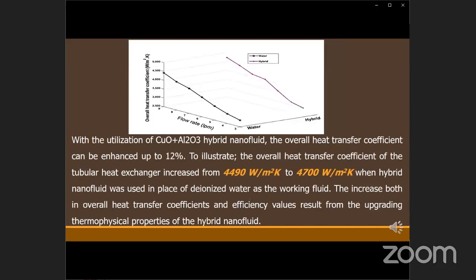heat recovery units. And finally, with the utilization of copper oxide alumina hybrid nanofluids, the overall heat transfer coefficient can be enhanced up to 12%. For instance, the overall heat transfer coefficient of the tubular heat exchanger increased from this value to this value when hybrid nanofluid was used in place of deionized water as a working fluid.